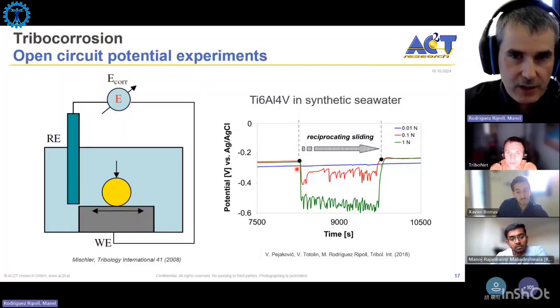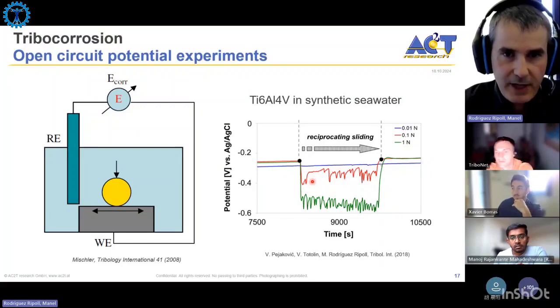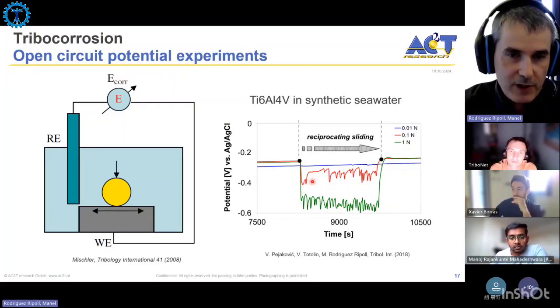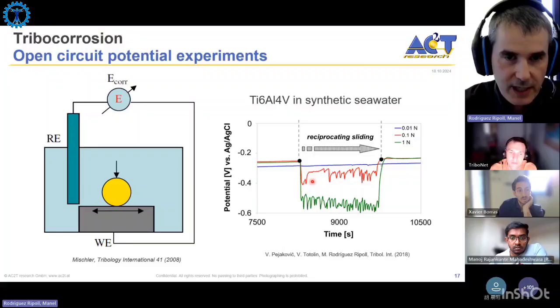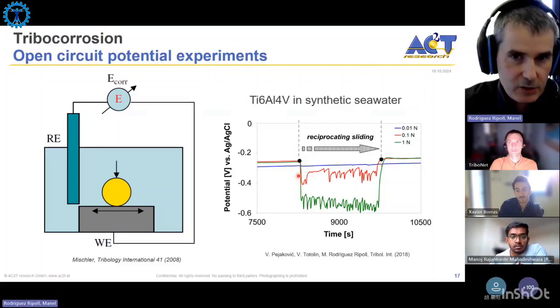This drop in potential is caused by a galvanic coupling. We have talked before about the galvanic coupling. Basically, when we mechanically break the passive layer, we expose the naked metal to the electrolyte. It means that the wear region becomes anodic, so the metal is corroding there, and the cathodic reaction, where the electrons get absorbed, occurs in the cathodic region, which is outside the wear scar. This galvanic coupling between the wear scar and outside the wear scar is responsible for the drop of the open circuit potential. And you see that this shift is toward cathodic values, toward less noble values, because our material gets less noble.